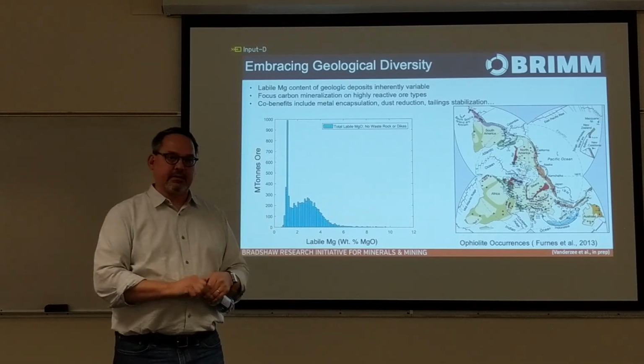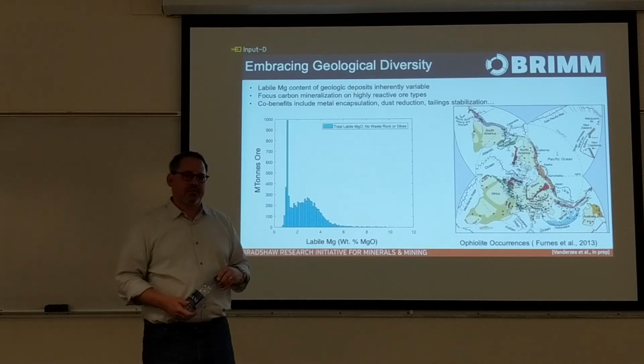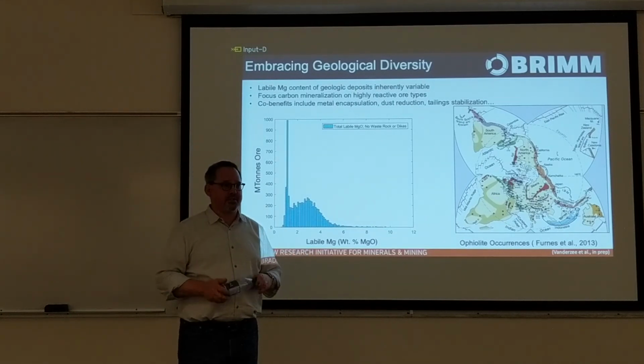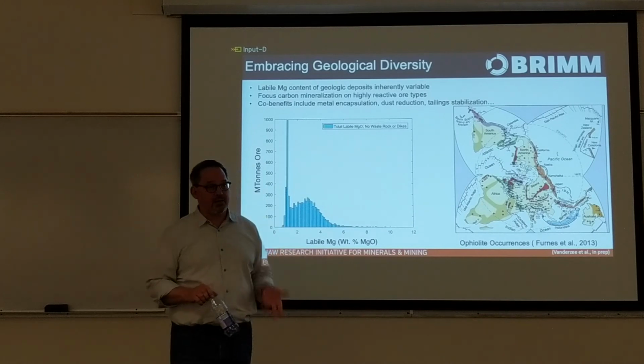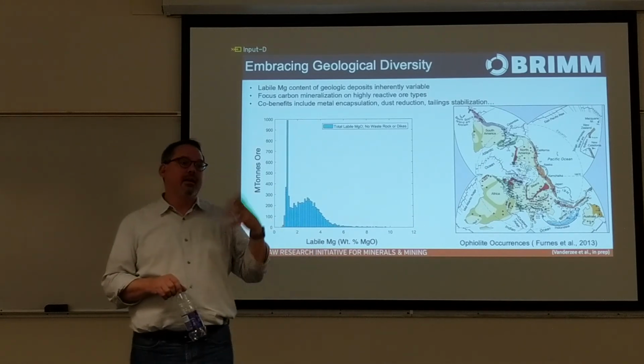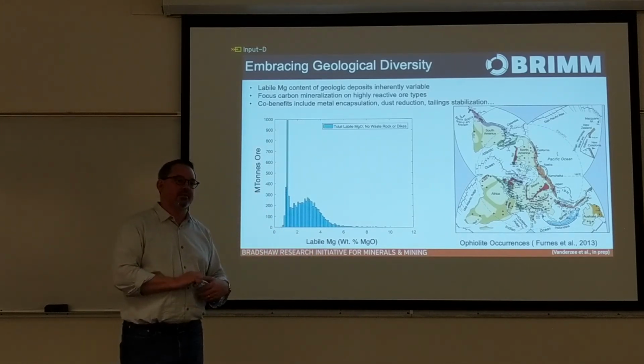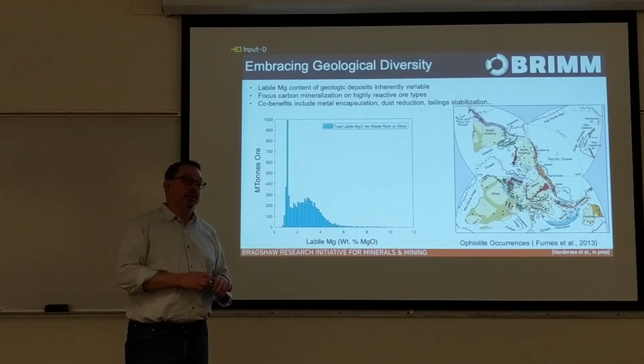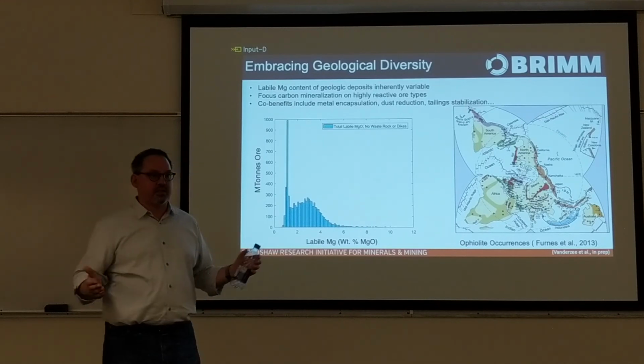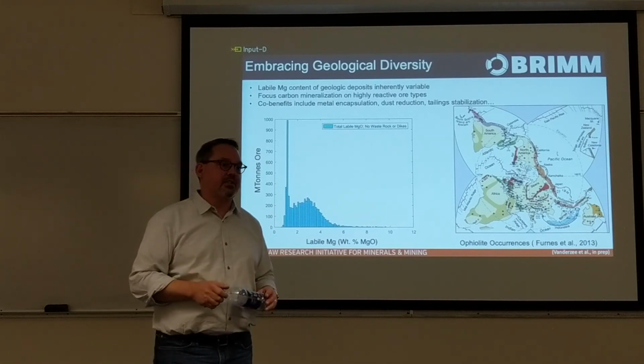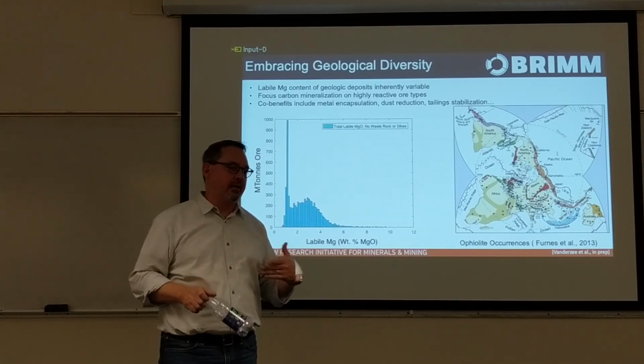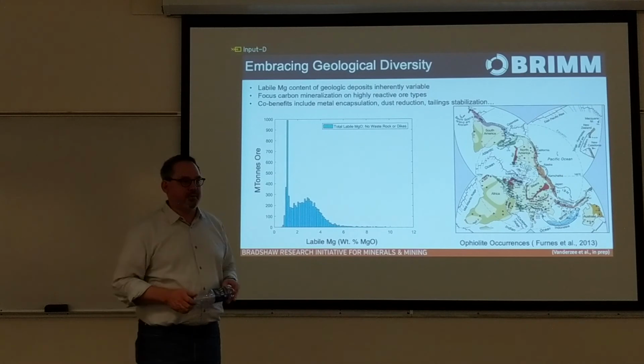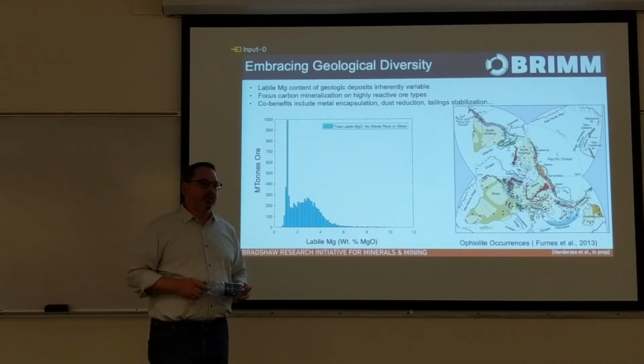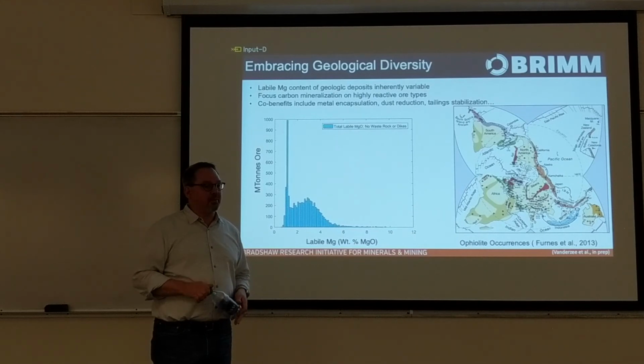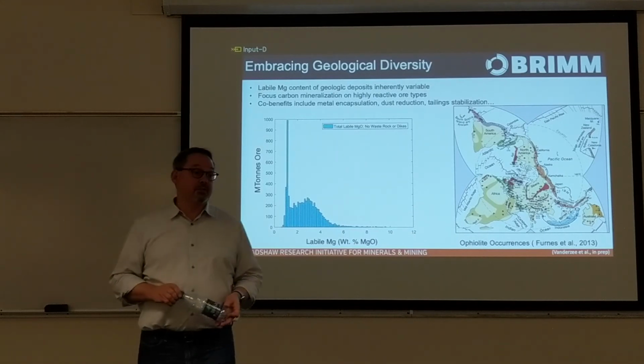When they had leaks at the tailings storage facility at Mount Keith, they were killing trees because of the salting. They were using bore water, so they were half seawater salinity to start with, and they have high evaporation. So certainly the processed waters are not good, but water use is strictly controlled, so they don't have a leakage entry. Our experience has been that the primary risk would be through water leakage, so we need to control that. And that's probably the only real risk for carbon leakage as well.